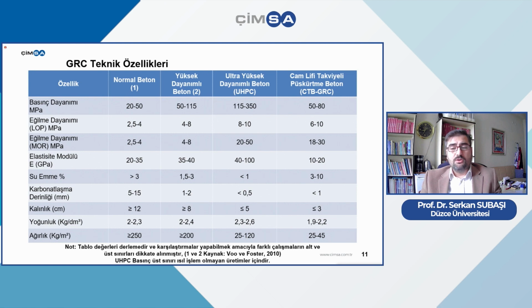glass fiber reinforced, of course, pressure resistance is 20 to 50 in normal concrete structures, but it is reaching up to 50 or 80 in GRCs. And also, the most important feature is the bending resistance, of course. LOP value in the matrix structure is showing us the resistance until it cracks, and it is approximately 10 megapascal. And when we look at the bending resistance MOR value, it is reaching between 18 and 30. When you produce these concrete types with some woven fibers, these values are rising. It is possible to make them better.